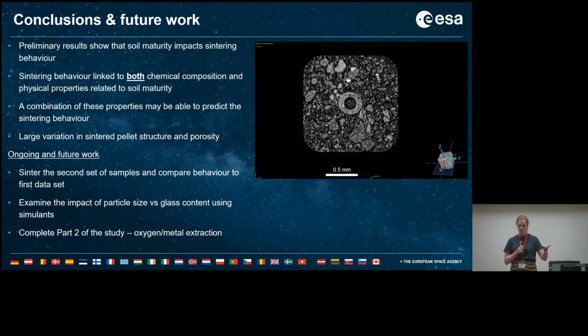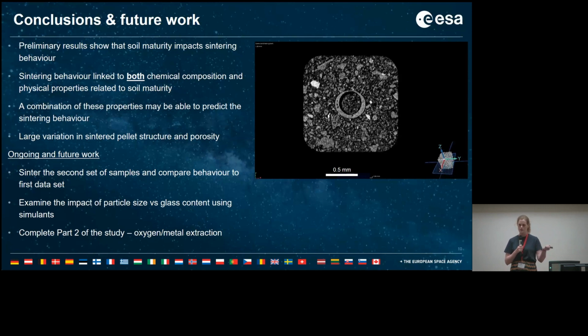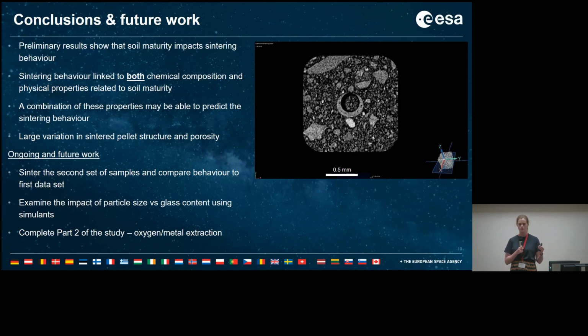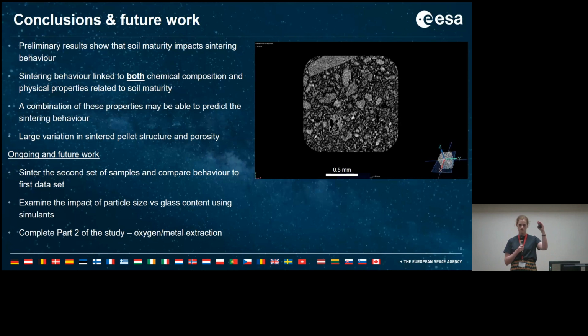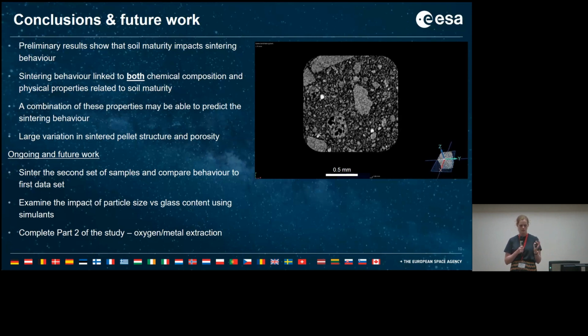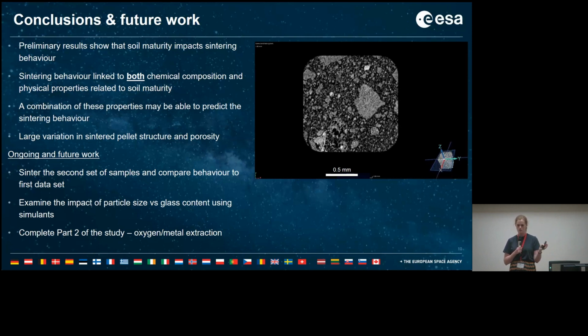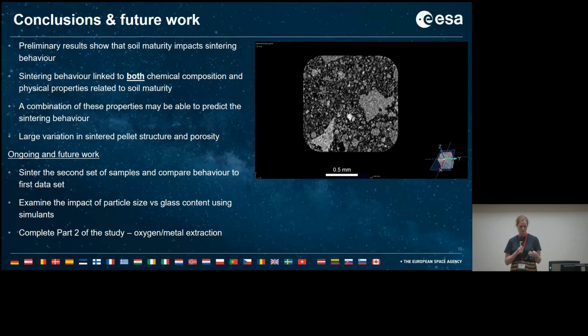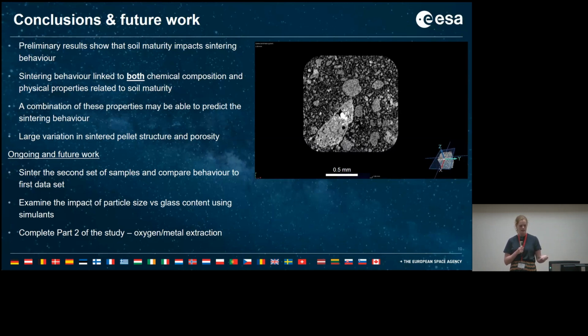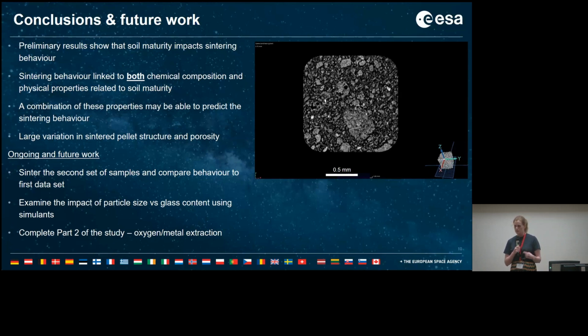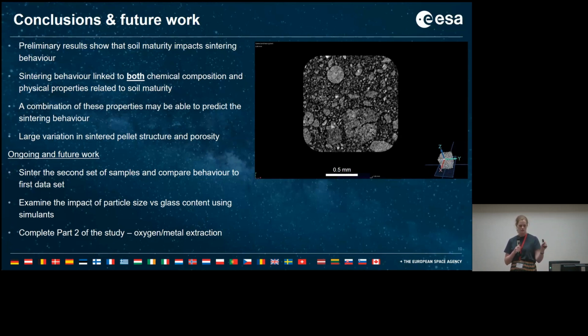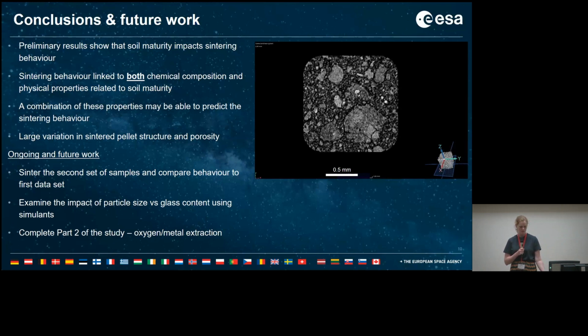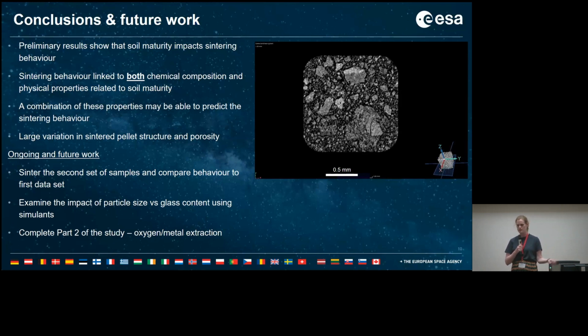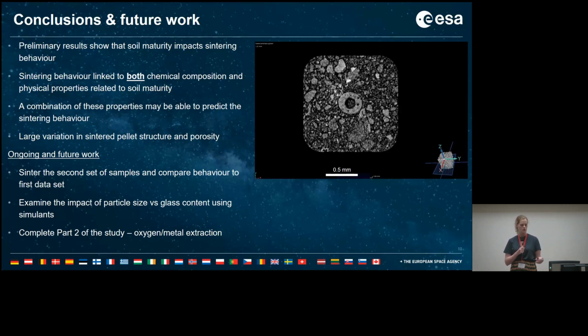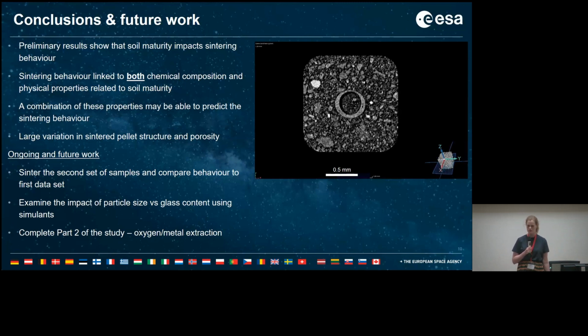And so ongoing work is obviously we want to sinter the second set of Apollo samples. Now that we know where the temperature is expected to be, we can define a more structured sintering process, a set number of steps, for example. And we want to examine the difference between particle size and glass content using simulants with different additives of different percentages of these things. And also then finally, of course, complete the second half of the study, which is to process these pellets using molten salt electrolysis.